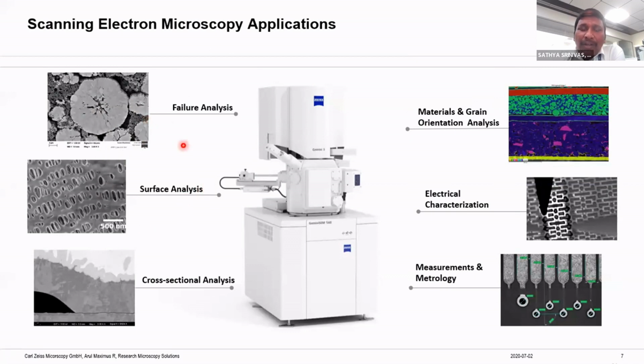And apart from failure analysis, even surface analysis studies for very beam sensitive samples. So for example, this is an electrode which is in a battery. After a particular number of cycles of usage, you want to see how exactly the degradation happened, because this is what defines the efficiency of the batteries, right? So these electrodes and all those things. After particular cycles you can know the surface degradation, what exactly the contamination or deposition is on any of the catalyst material or the anode, these electrodes, right?